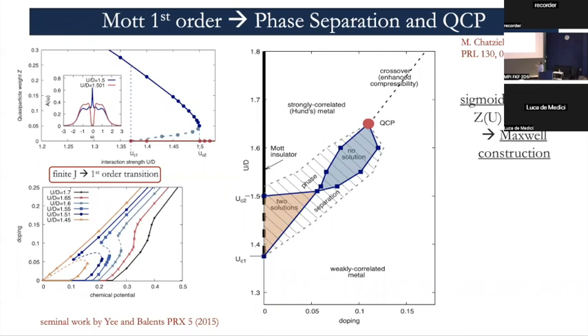So here what you have is a transition between a weakly correlated metal and a strongly correlated metal, which is the proper doped Mott insulator that we will portray later as the Hund's metal zone. And then you have a first order jump between these two solutions, because you have this unstable metallic branch. Here it is unstable clearly because you have this negative compressibility. This is doping, so density versus chemical potential, and when it goes monotonously growing, the system is stable, but when it goes back, it has a negative compressibility in these dashed zones. So it's unstable. So you get phase separation.